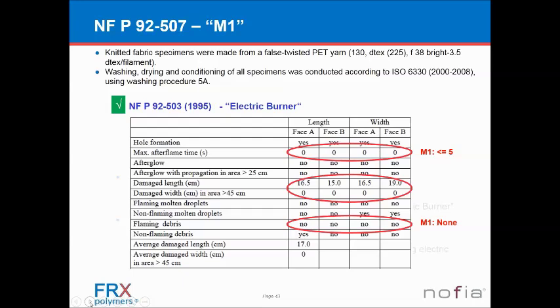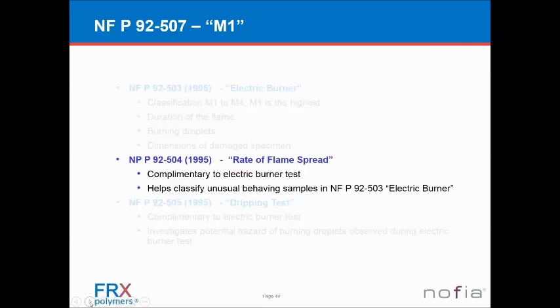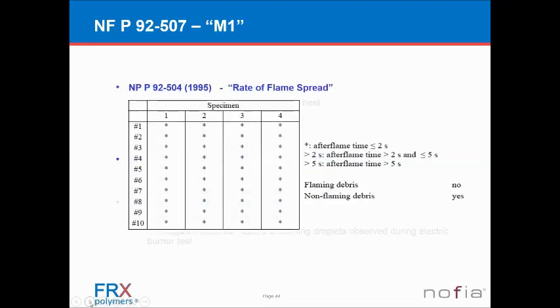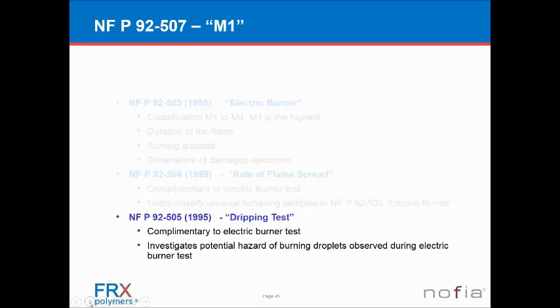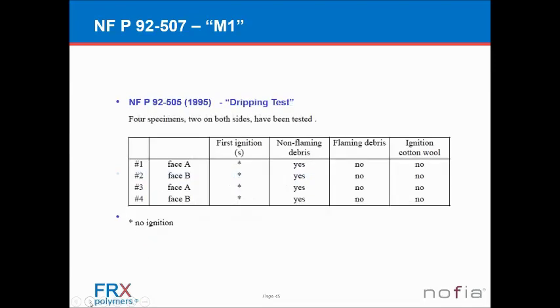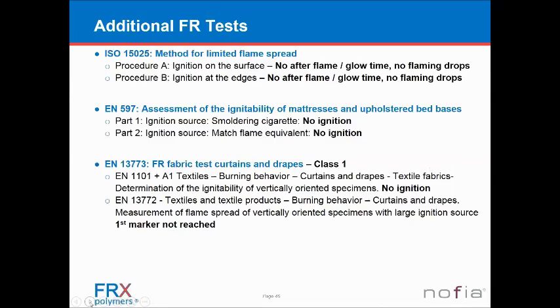If you have a meltable material, and polyesters are, then you need to continue with the 504 test, which is the flame spread test. Here you burn holes in the fabric and look at how quickly the flame extinguishes, which should be less than 2 seconds. In our case, there was no after flame time at all, and no burning debris from the fabric. Then finally you have what I call the dripping test, where you look at whether there is ignition, flaming debris, or ignition of the wool underneath the sample, and there was none. So when you fulfill all of these tests, you have an M1 rating.